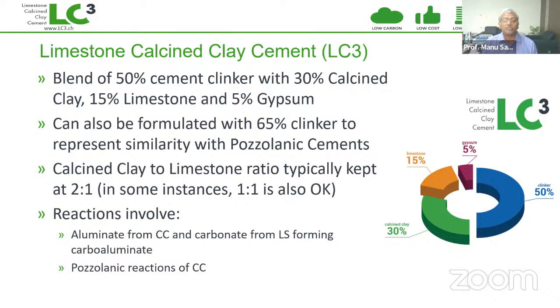So essentially it's a 50% replacement overall of the cement clinker with the mixture of calcined clay and limestone. Of course, gypsum has to be modified based upon the chemistry, to ensure that we get the best performance from LC3. Generally, you may also see in some examples from Cuba that they've also looked at it as a complete pozzolanic cement where 65% clinker is used. The calcined clay to limestone ratio typically in LC3 is 2:1. And in some instances, even 1:1 can be permitted because not all of the calcined clay gets a chance to actually react.